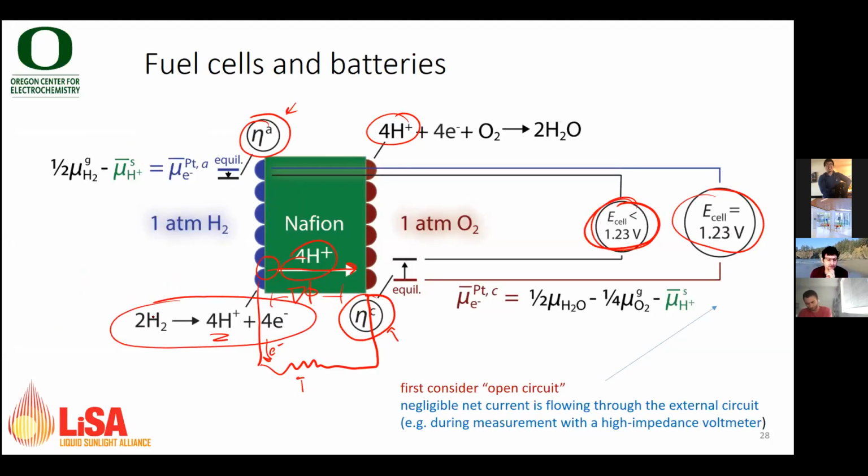The flow is the same in both directions. It has to do phenomenologically with something people call the transfer coefficient. Shane will talk about that. And then practically, it also has to do with whether your catalyst is actually chemically changing as a function of potential. Actually, all the catalysts that do oxygen reduction and oxygen evolution are completely different surfaces under those two reaction conditions. So there's no reason that they need to be microscopic reverse mechanisms of each other, because they're actually different surfaces.